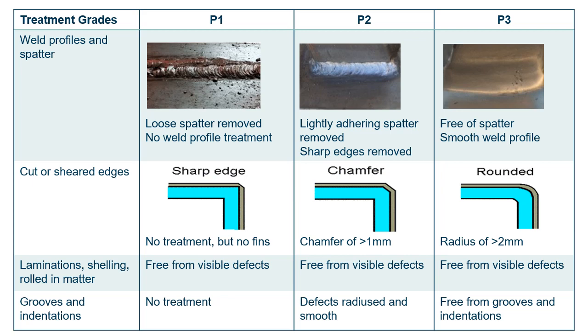For grooves and indentations, no treatment is necessary for P1. Defects are radiused and smooth for P2 and completely removed or filled for P3. These examples should give an indication of the defects and how they must be treated.